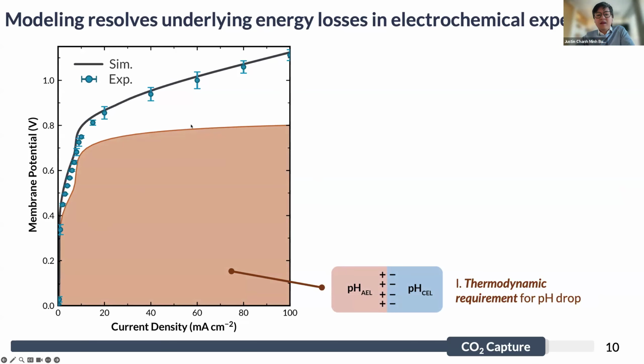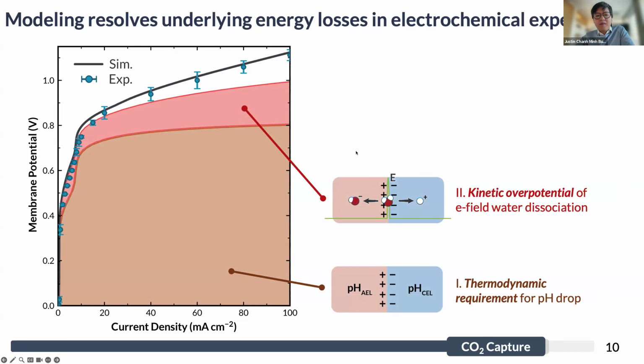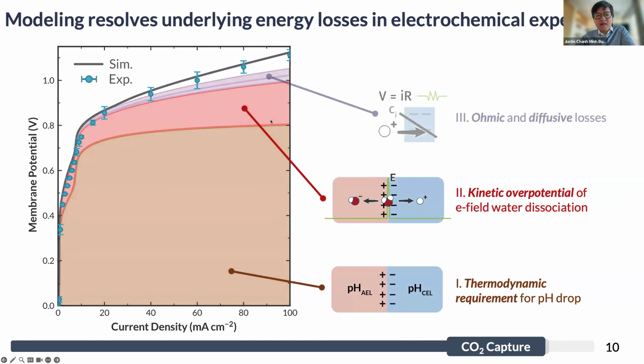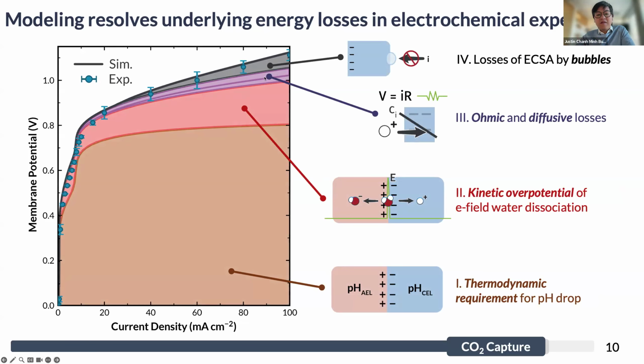But you can see there's a lot of headspace above just the thermodynamic requirements for the pH drops. You see there's a lot of losses associated with the kinetic overpotential, so the energy required to drive the catalysis of water dissociation, as well as potential associated with losses due to the ohmics through each of our membranes. And then finally, we see an interesting and non-negligible loss associated with the coverage of bubbles on our membrane.